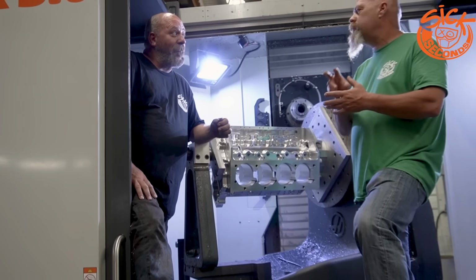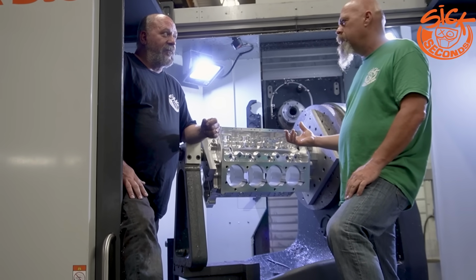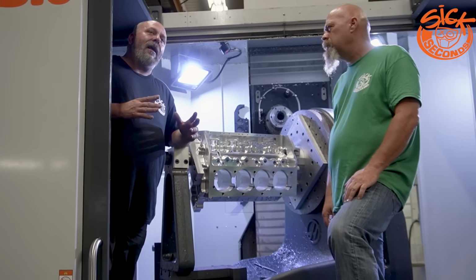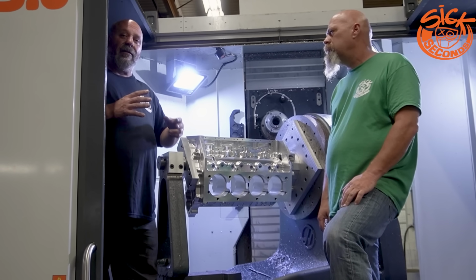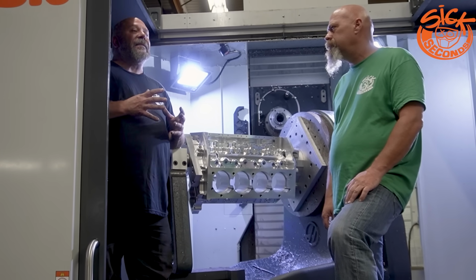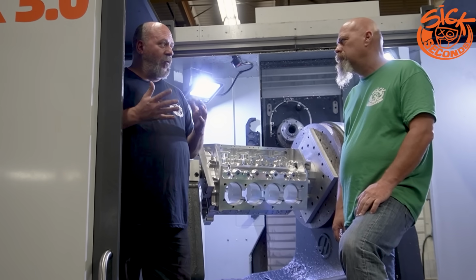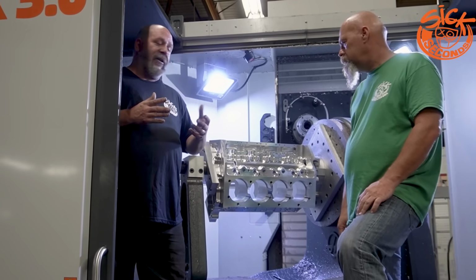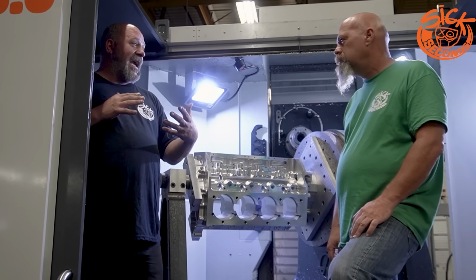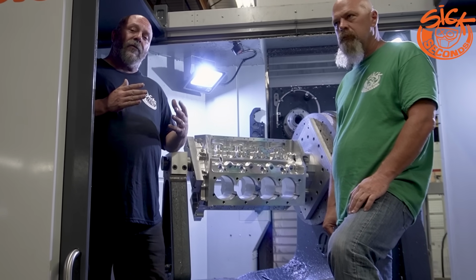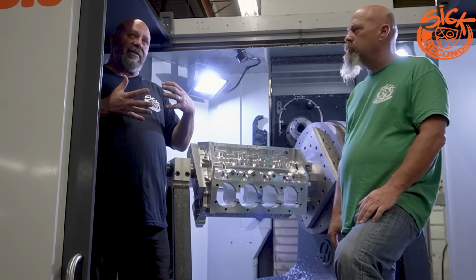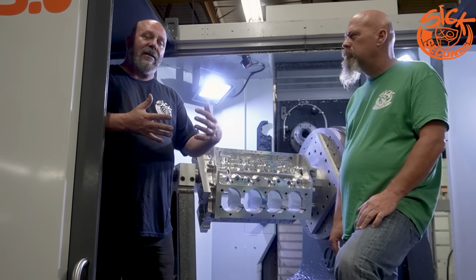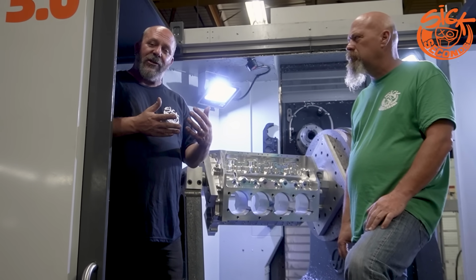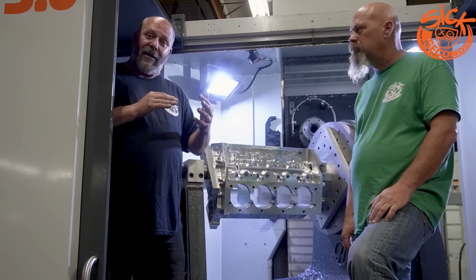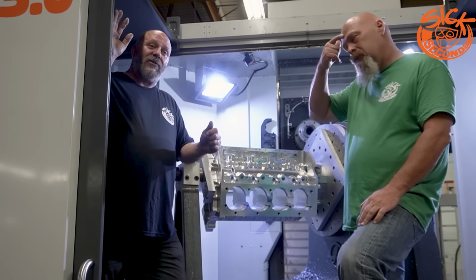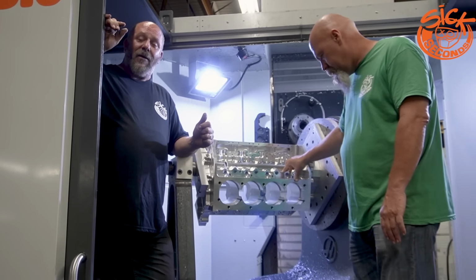Was that because too much material was taken off before heat treat, or not enough material? Not enough material. So the heat treat penetrated in, but it didn't stress relieve. The other thing heat treat does for material is relieve the stress within the material from when it's cast or however. There was too much material left in it, and it left stress within the material. As we were machining it out, it started stress relieving on its own, and that made our bores go out of round. So we learned from that one that we could not leave that amount of material on.